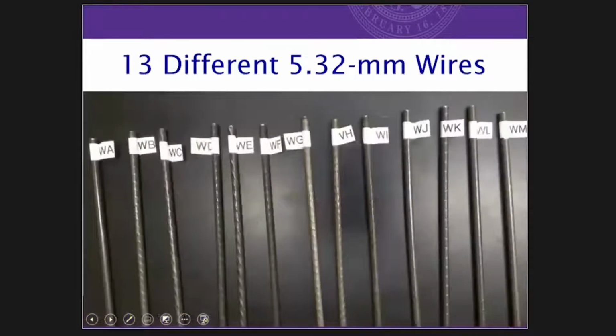I started working with indented pre-stressed concrete wires back in 2008. And in 2011, we got our first FRA project looking at transfer lengths. At that time, almost all the plants in the United States were using 5.32 millimeter wires, with the exception that one plant used an indented strand. So we worked with LB Foster CXT Concrete Ties. They provided 13 different 5.32 millimeter wires from around the world that were used in pretensioned ties. And these all had different indent geometries and different types of indents. And so we wanted to characterize the bond of that.